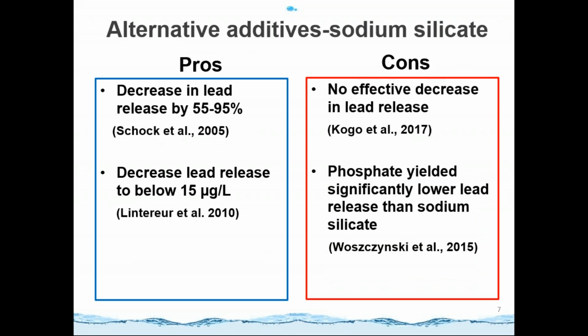After carefully reviewing the literature, we find some of the studies report positive results, but some report negative results. For example, in 2005, Schock et al. indicated they observed a decrease in lead release of 55 to 95% when they switched the corrosion inhibitor from polyphosphate to sodium silicate. And in 2010, a report observed lead release decreased to below 15 micrograms per liter using sodium silicate when they tried to feed blended water.